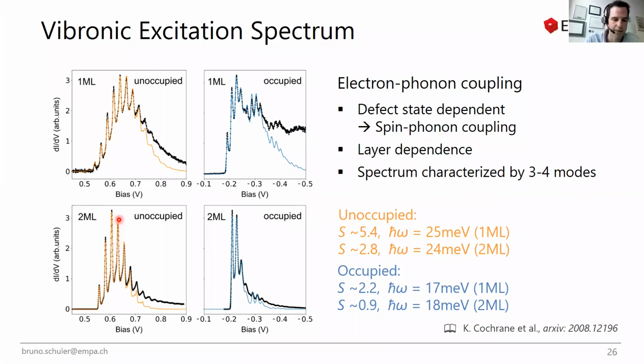Because also the shape of these peaks, we modeled them by a Gaussian and not by a Lorentzian. So this gives us a better fit. So at the end, it's on the scale that you might expect just from the sheer distance between defect state and graphene, but the shape as a Gaussian tells us there might be some contribution from low energy acoustic phonons.